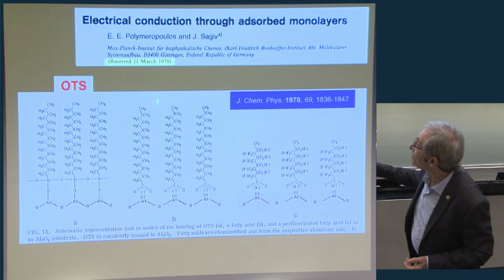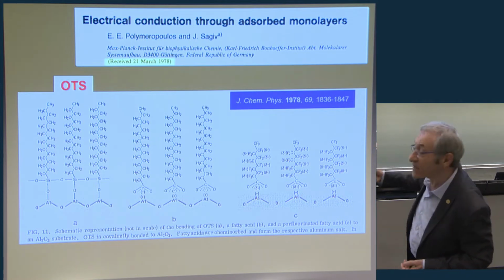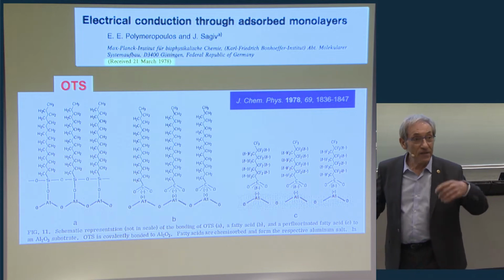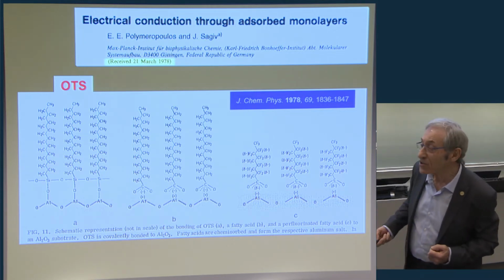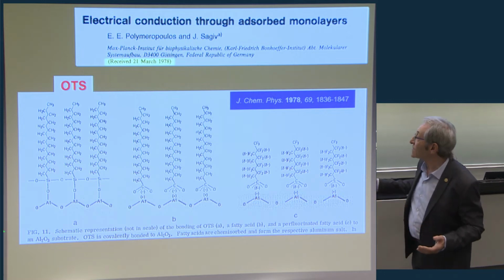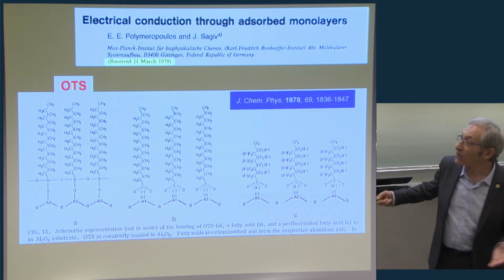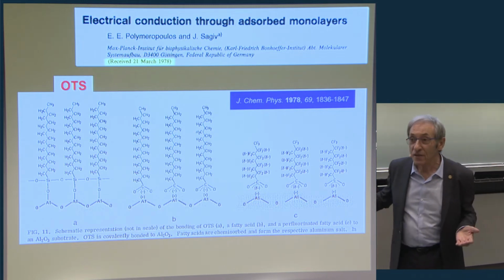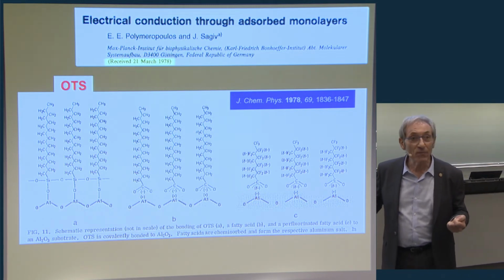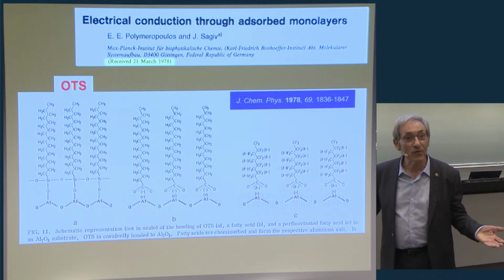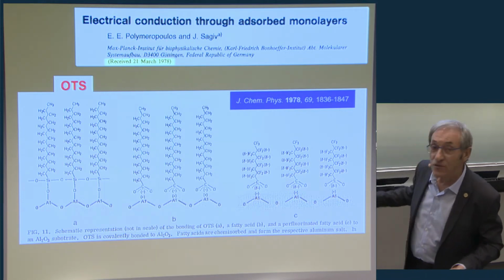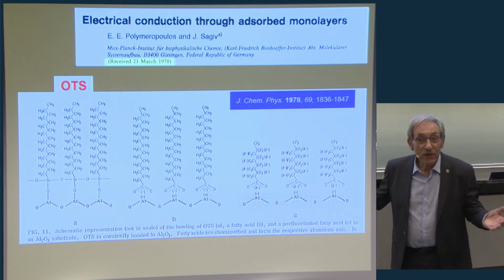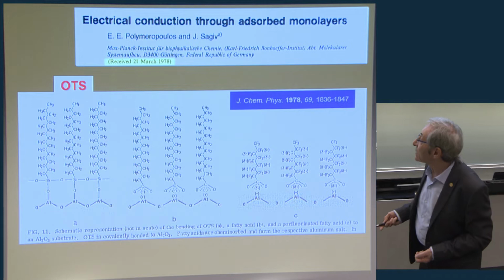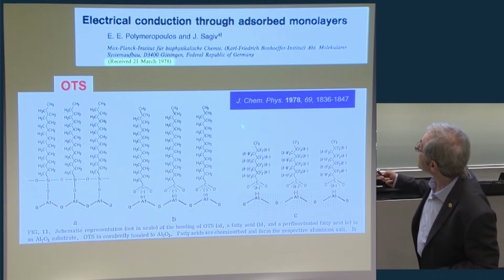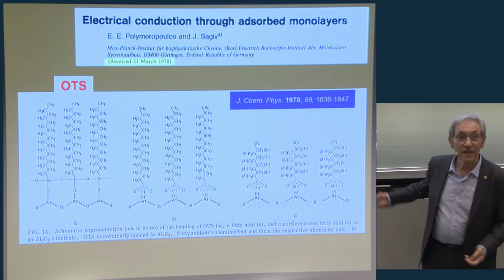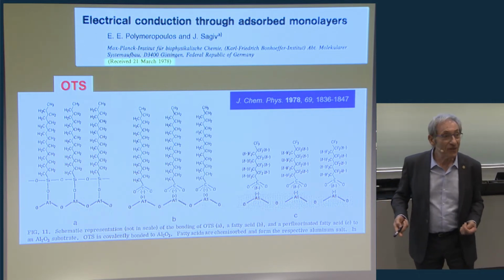We were looking at electric conduction through these monolayers, which we call adsorbed monolayers, to distinguish them from Langmuir-Blodgett monolayers. To our surprise, even in the first trials, it turned out that these monolayers are much better insulators. With Langmuir-Blodgett, it was difficult to obtain more than about 50% good samples. The rest were short circuits. With these monolayers we had more than 90%. At that time, we had just started playing with them. This was published, as you can see, in 1978. So this is the date that I put for the birth of this monolayer.